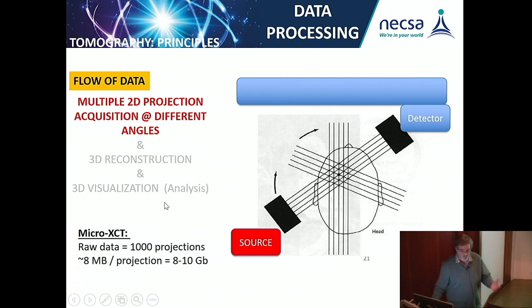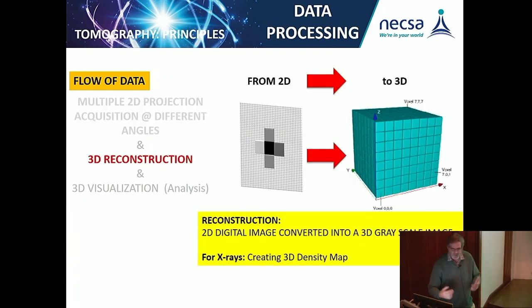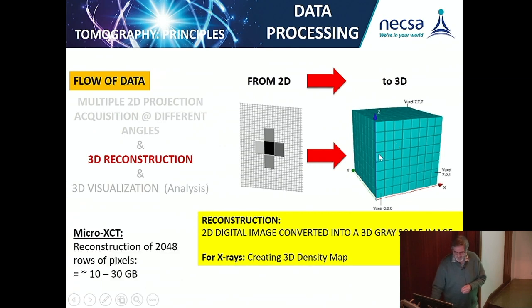The next part of the data processing is the reconstruction process, and in the reconstruction process you have to go from 2D to 3D, and that is the reconstruction process which Cormack actually started and put into practice. You end up with a 3D virtual volume at the end of the day. For this reconstruction and 3D volume, you end up with 10 to 30 gigabytes of data. That doesn't depend on the size of the sample. If you scan a cell phone, that data is generated. If you scan the point of a ballpoint pen, that data is still generated, but with higher spatial resolution at the end of the day.